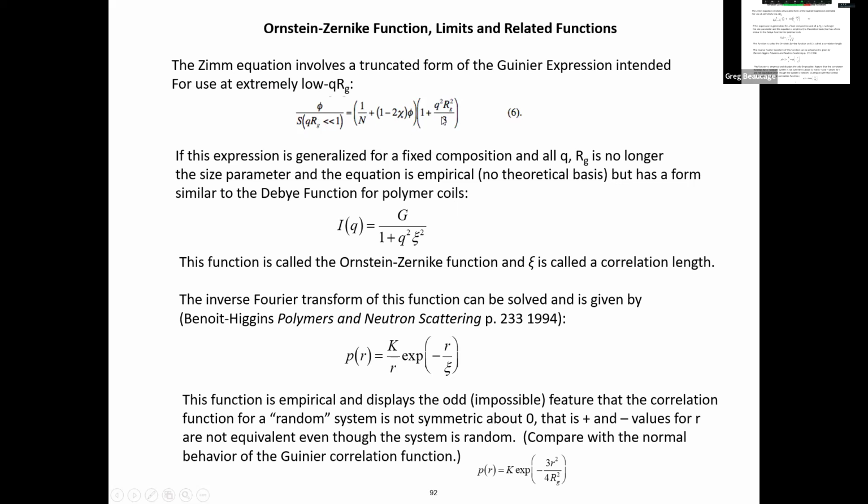You just basically wanted to linearize the exponential, so you did that. Then you had this thing that was already linear in concentration, and they just multiplied the 2 together. It's almost like saying the scattered intensity would be the form factor, which would be this number, and the structure factor, which has something to do with this number, multiplied by each other gives you the intensity. So it kind of looks like that, but that doesn't work in inverse, number one. And number two, it isn't true. That isn't how polymers work. If you have fractal things that are intertwined with each other, it doesn't work that way. So I'll show you how it actually works.